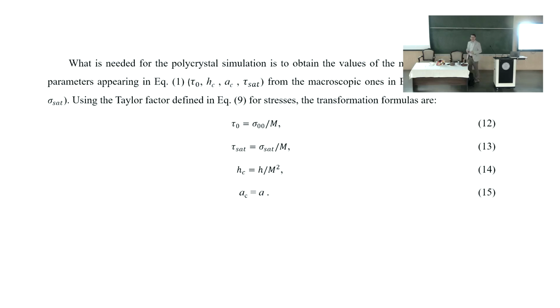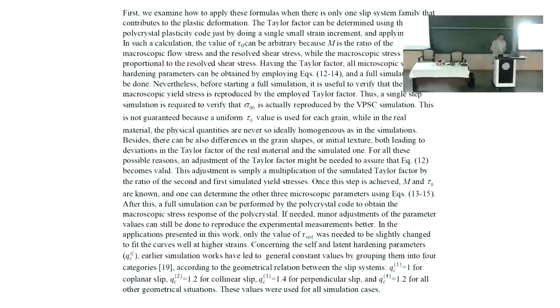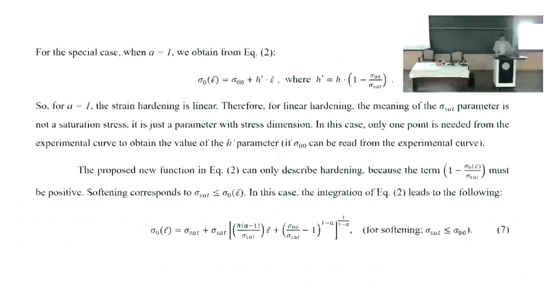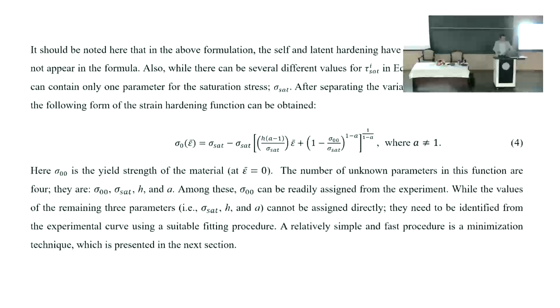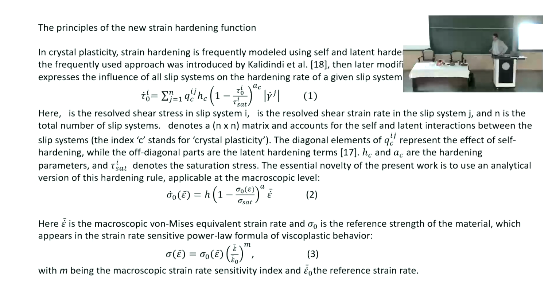So we have these initial parameters, and then we can do the polycrystal plasticity simulation. Now this polycrystal plasticity simulation is quite tricky, because, as I said, it uses a much more sophisticated hardening rule. For that hardening rule, I'm going back to the initial slide which showed how we started. This is the hardening rule we have to use in simulation, in crystal plasticity.